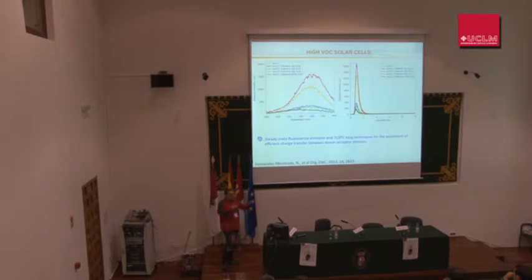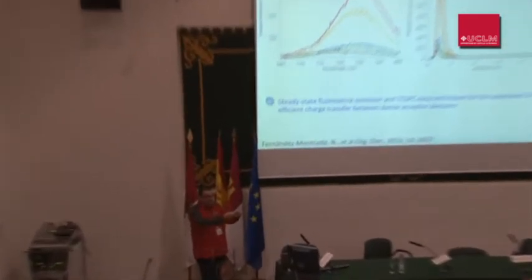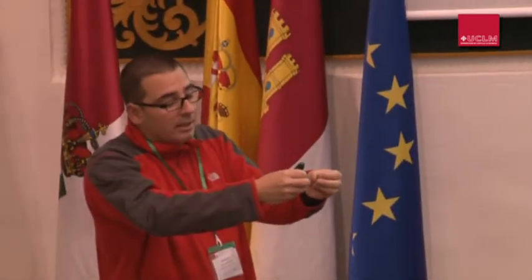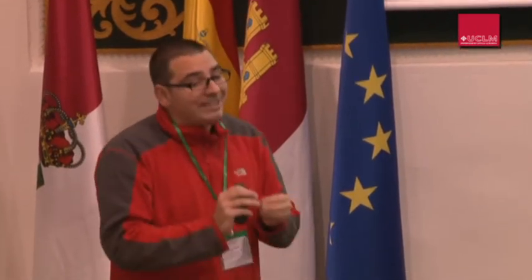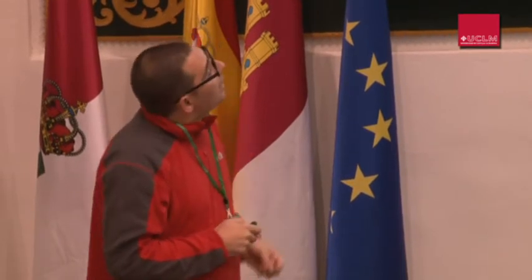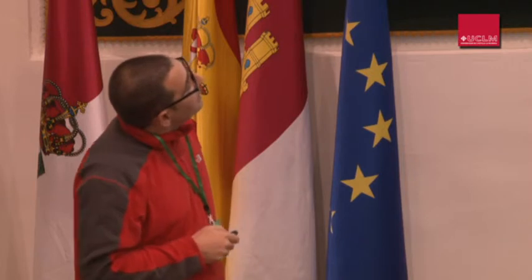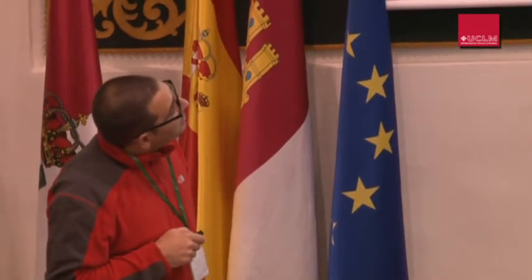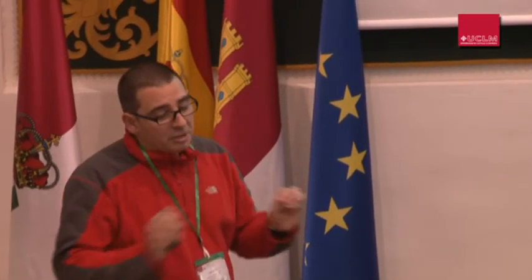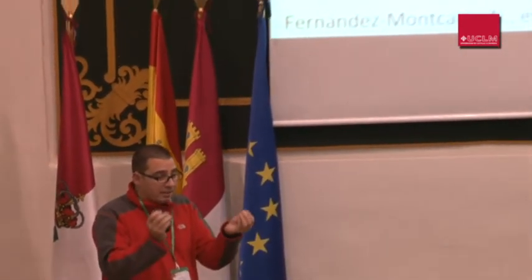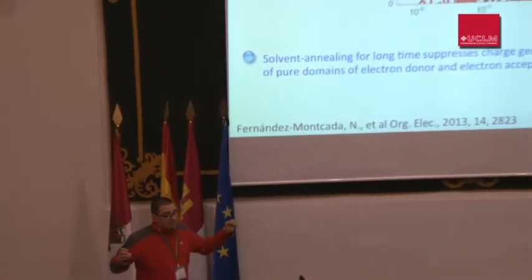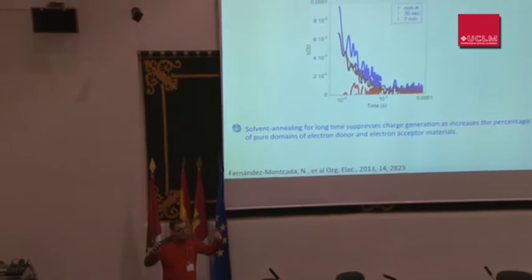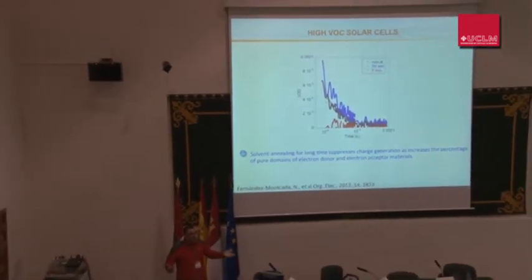One is they split and form free charges, polarons, or they remain there, which up to 1 year ago people didn't think that this could happen. They remain there for several nanoseconds, and then they go back to the ground state. It is what is now called CT states, charge transfer states. And then you need other techniques like laser transient spectroscopy to really check that this decrease in fluorescence emission is not only the formation of CT states, excitons, it's also the formation of free charges, because this is what you want. You want free charges that move and can get collected at the contacts and produce voltage and current.